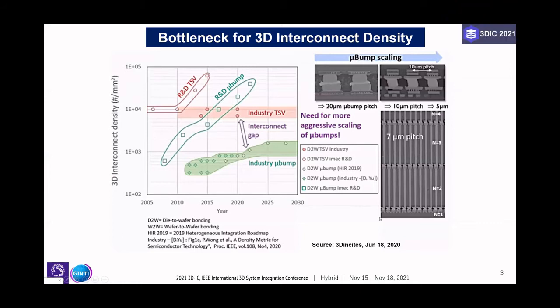Okay, so at the R&D level, we are able to increase the interconnect density. But if you go for production level, you have to stack your dies. Here comes your TSV and micro joint problem. At the industry level, we can make up to 10,000 TSVs. But when you are going to join your top die and bottom die, your TSV is going to land on your bottom micro bump or copper pad. So the size of the micro bump causes the real issue here.